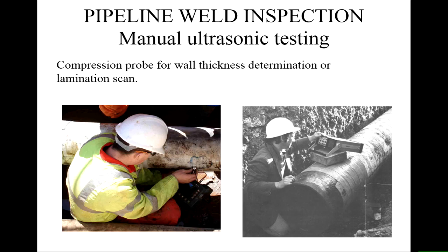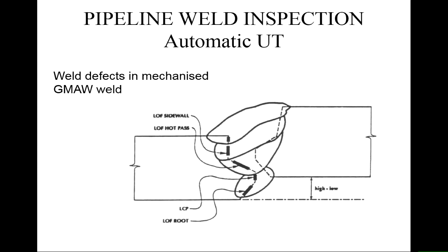So on site, I think the main use of these manual tests with this simple compression probe is for looking for these laminations, just so you can reject a pipe segment. You can have lots of defects in lots of positions, and that's where an automated system can tell you a lot more about it. So here is a mechanized weld in a badly fitted up system, and you can have lack of fusion pipes in the root regions here. You have lack of fusion, in fact, anywhere in that system.